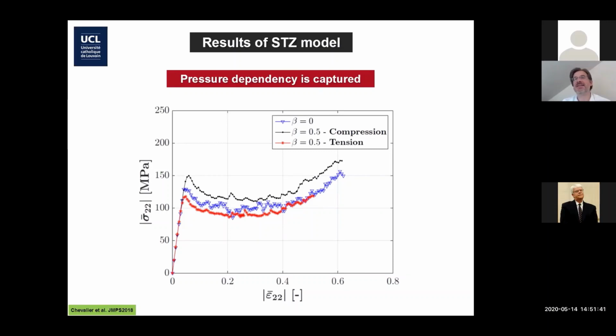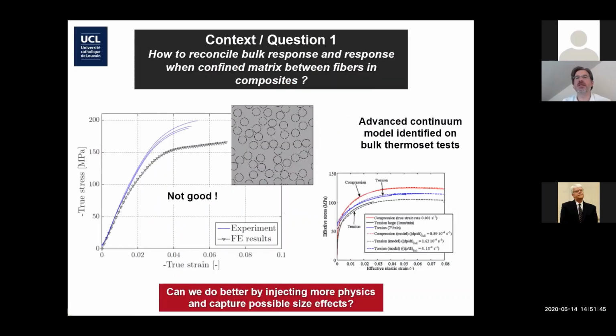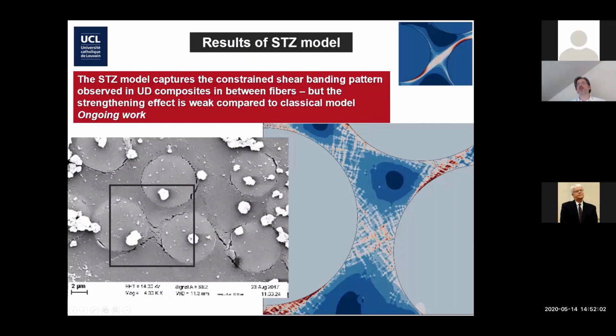Great. So with the beta parameter, you can introduce pressure effect, but that's not a big deal. No question now. Are we solving our problem from the beginning, that with this more physical model, we can capture better the response of a UD composite? We have mixed answer at this stage. This is ongoing work. We certainly capture the plasticity pattern when we simulate a part of the UD with the STZ model, and you compare with experiments, you see a fine pattern here that is in very good agreement visually with the experimental data, and as well with recent DIC measurements that I forgot to put. This is the pattern you're getting with the Drucker-Prager model. So it's not so bad, but you don't get these several shear bands pattern that we capture here. This is the positive message.